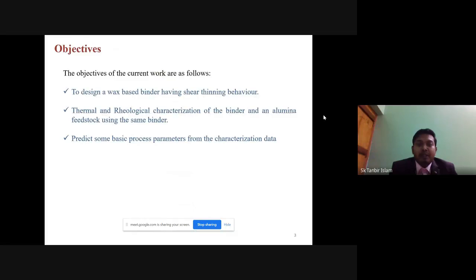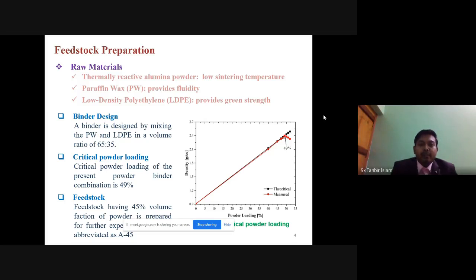The objectives of the current work are as follows: to design a wax-based binder having shear thinning behavior, then thermal and rheological characterization of the binder and an alumina feedstock using the same binder, and predict some basic process parameters from the characterization data. Here we have used thermally reactive alumina powder due to its low sintering temperature, and as a binder we have used paraffin wax and low density polyethylene. We can see from the graph that for this particular powder binder combination, 49% is the maximum powder loading that could be provided, and that is called critical powder loading. That's why we have taken a 45% powder loading feedstock for our further experimentation.